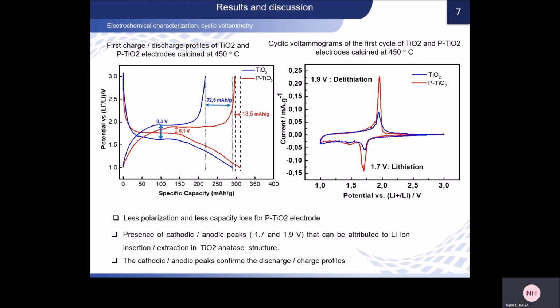Our cyclic voltammetry technique shows the presence of two cathodic and anodic peaks at 1.7 and 1.9 volt respectively, which can be attributed to the insertion and extraction of lithium ions in the TiO2 anatase nanoparticles. So these cathodic and anodic peaks confirm the results obtained with the galvanostatic discharge charge profiles.